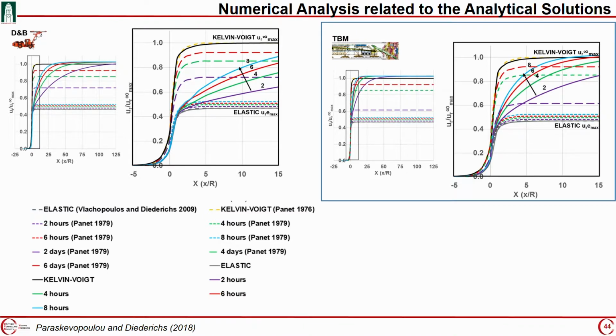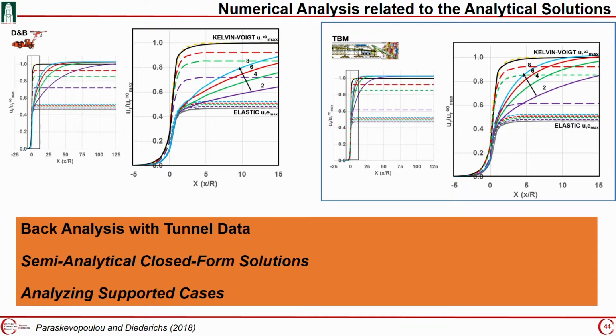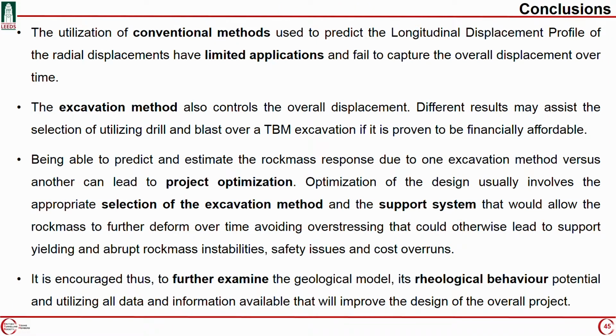And again, I have put here the analytical solutions and the numerical results. Analytical solutions are the dashed lines. Numerical results are the continuous lines. What I want to show here is that you cannot have both. You can have both in numerical modeling, but you cannot use analytical solutions to capture both the effect of the tunnel advancement and the time-dependent behavior when you're designing. Right now, I'm back analyzing this with real tunnel data, to produce semi-analytical closed-form solutions you can use for both, that account for both effects, and for analyzing supported cases. I hope I didn't bore you with all of this, but I would like to leave you with these three conclusions.